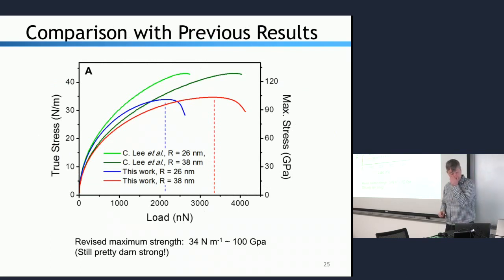More importantly, if you look at the maximum stress as a function of load, what we see in the original model that we put out is that the maximum stress doesn't go linear, it kind of curves up, not as a perfect square root, but you can still see it curving off like this and only really flattening off at very, very high loads. But because of these higher order terms, this stress versus load curve actually flattens out earlier.